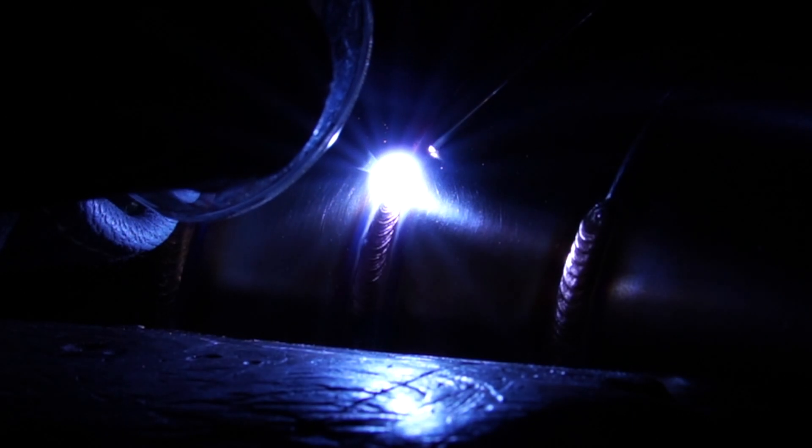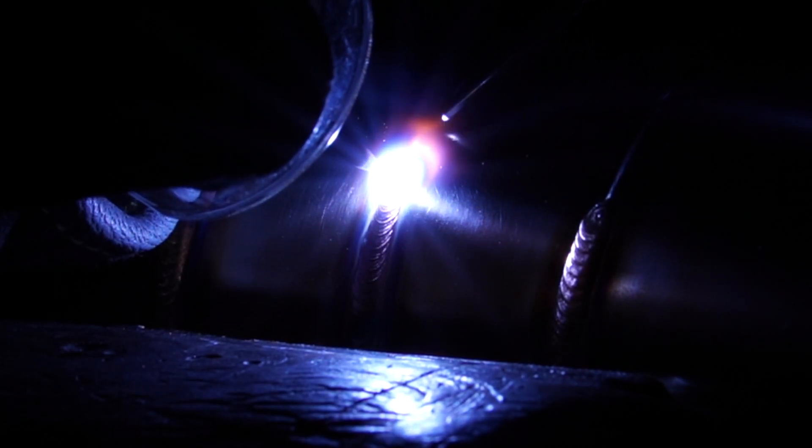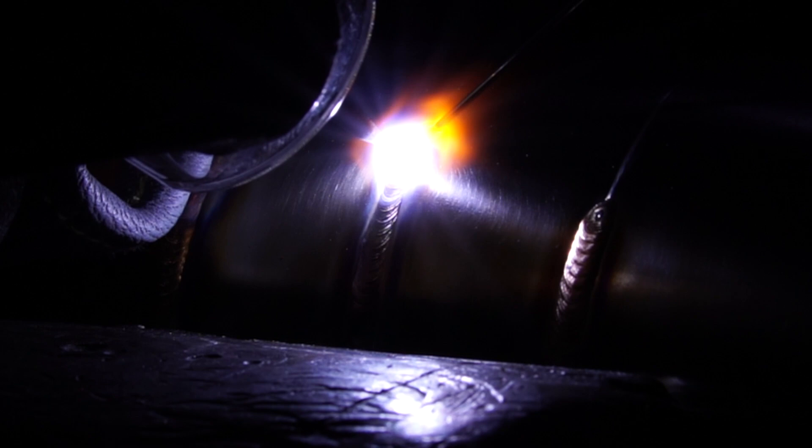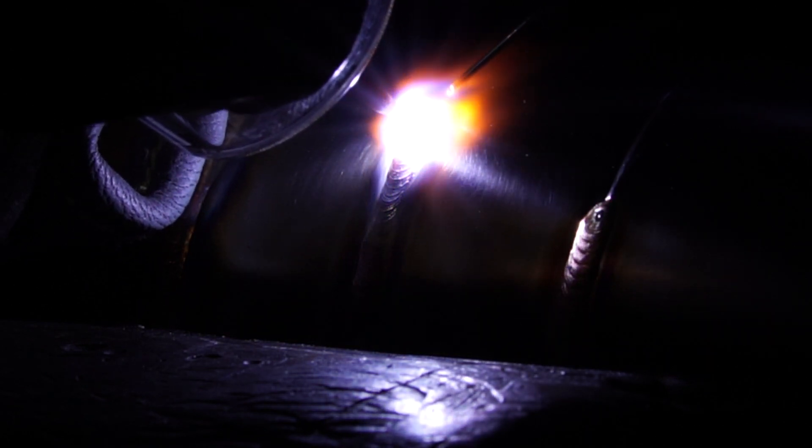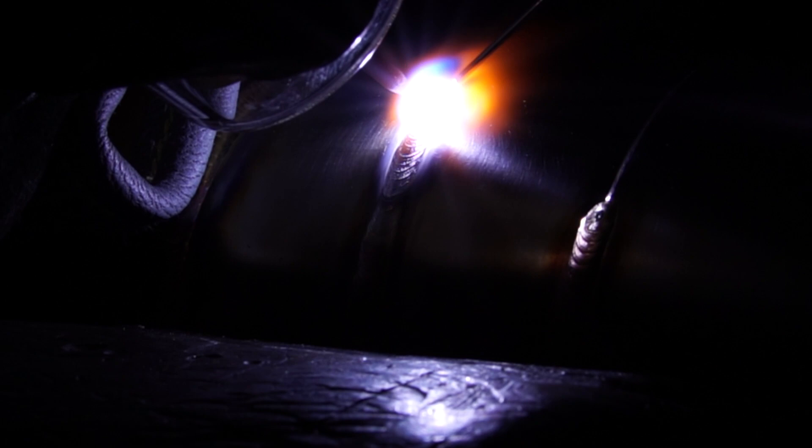Hold the tight arc and imagine a tangent plane on the tube as you're welding along. You want a push angle on your tungsten, but you want to try to keep your tungsten perpendicular to the tangent plane as you weld around the tube's radius. You can have a tungsten push angle of about 10 to 15 degrees. This is not only important for maintaining good gas coverage, but it will also assist in focusing penetration and preventing your ripple spacing from being elongated.